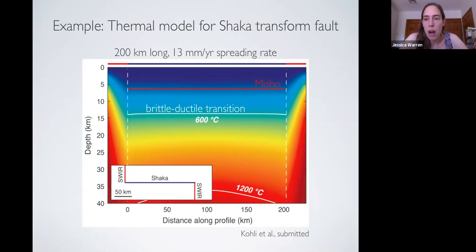degrees C, which is based on both lab observations actually by Margaret Betcher for where the transition from brittle failure to ductile flow occurs in olivine, which is around 600 degrees C, and also constraints from seismicity, which shows that in general, the large earthquakes at least don't occur at deeper than 600 degrees C. So the brittle ductile transition is defined from the rheology, both from the rock deformation constraints and also the seismology, whereas the moho is just defined based on kind of classic oceanic lithosphere structure.